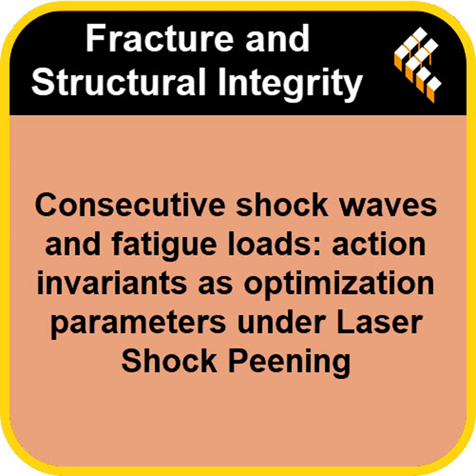The way fatigue cracks grow also shows self-similarity. This is captured in the well-known Paris law. The Paris law describes how fast a crack grows under cyclic stress. Exactly. And the exponent in the Paris law, usually called m, is also often found experimentally to be close to 4. Wait a second. The exponent is also 4, for both the nanosecond shock wave and the slow fatigue crack growth? Close to 4, yeah. It's a remarkable coincidence, if you can call it that.